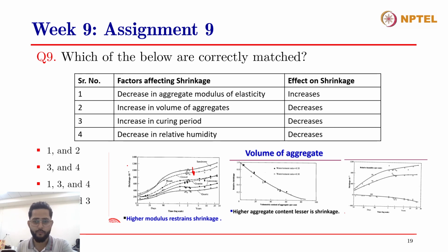When you increase the volume of aggregates, again you can see this view graph. When you increase the volume of aggregates in concrete, the paste content gets reduced, and therefore shrinkage is occurring in the paste part of concrete. When the paste content gets reduced, the shrinkage will also be reduced, and you can see that this is the increase in volume of the aggregates and how the shrinkage is reduced, right? So increase in volume of aggregates again decreases the shrinkage.